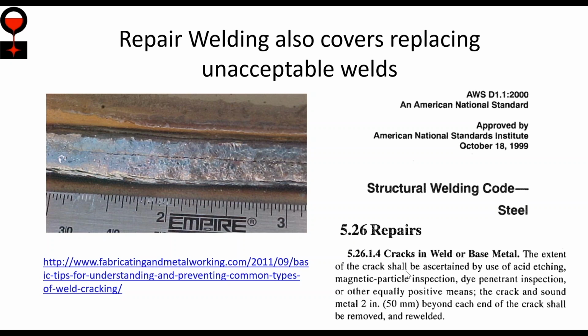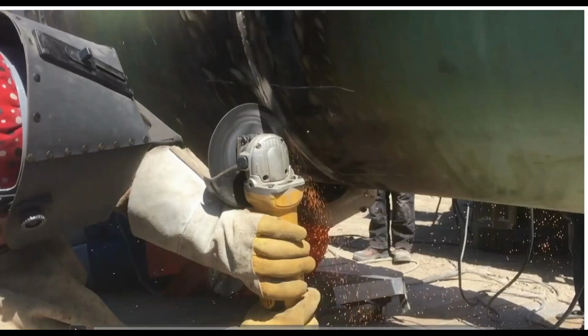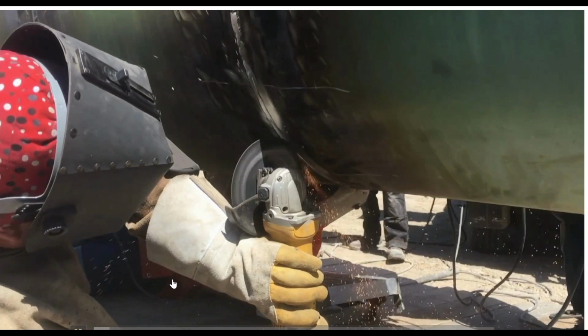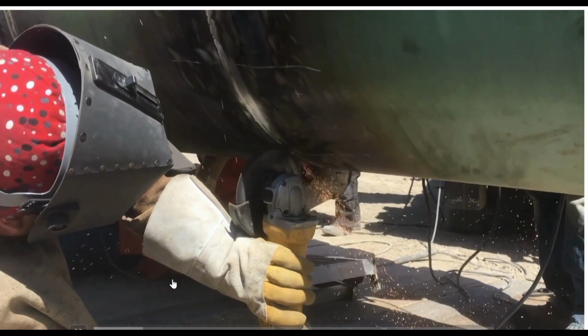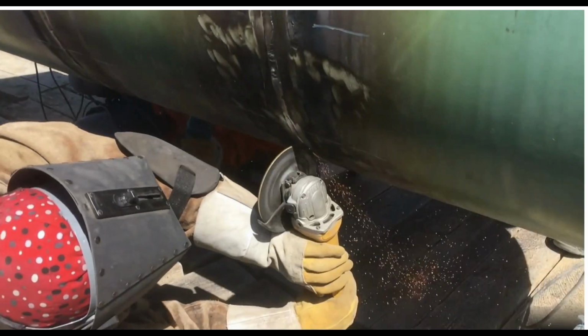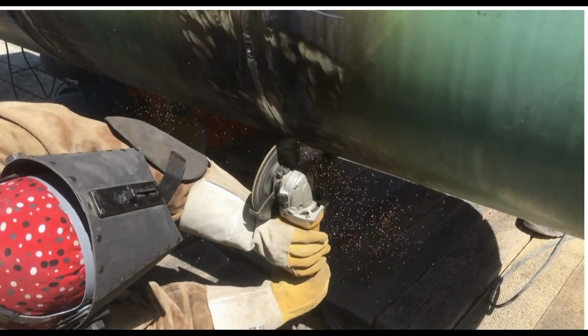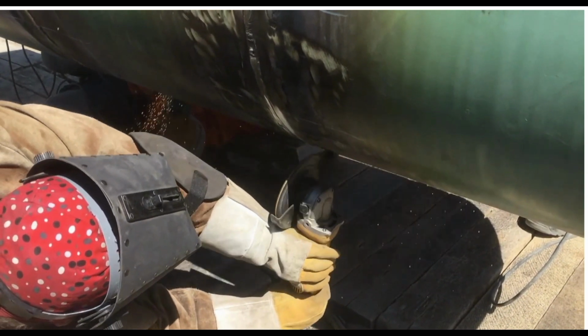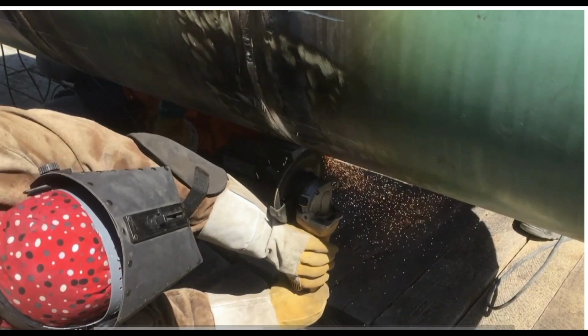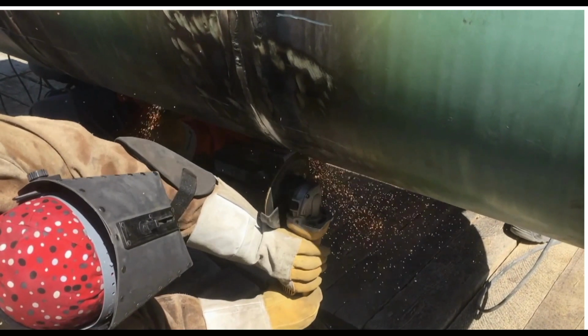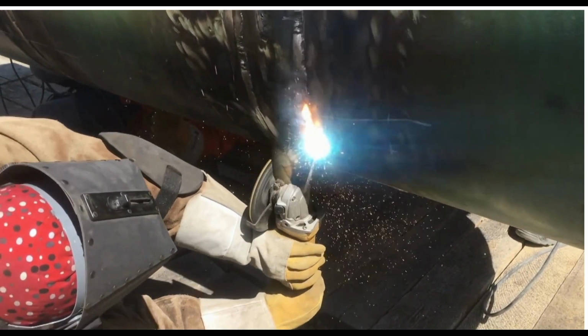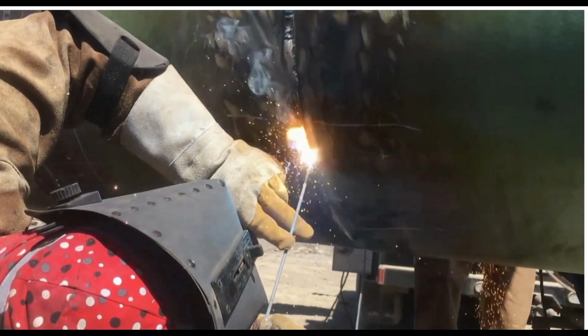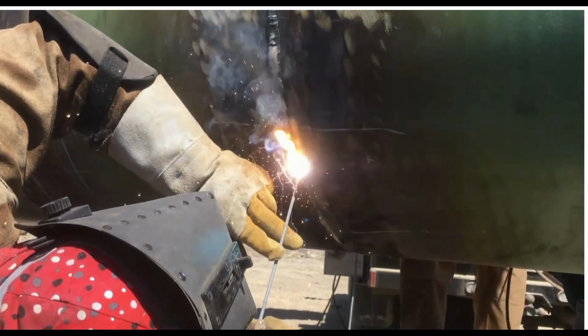repairing a weld. And you can see that in this video. This is somebody getting qualified and welding a pipeline to do a repair weld. So he's actually grinding out the non-compliant weld that had slag and failed to meet the ultrasonic requirements. And then he's going to have to re-weld that section. And then that section has to comply with the requirements.